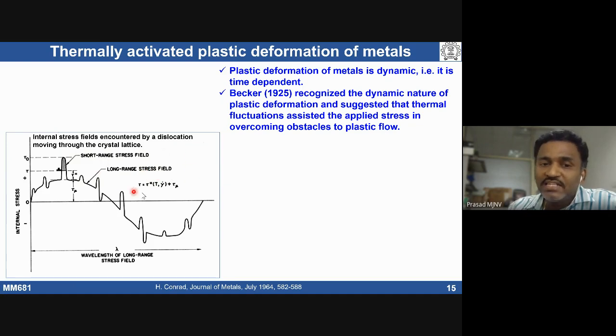This long range stress field cannot be overcome by thermal fluctuation. That means if you give some thermal change, a temperature change, that will not overcome the long range stress field obstacles. So those barriers are called athermal barriers. Whereas the short range stress field obstacles can be overcome by applying some thermal vibrations, some thermal fluctuations, that can assist your applied stress, so they can be overcome very easily. So those are called thermal barriers.